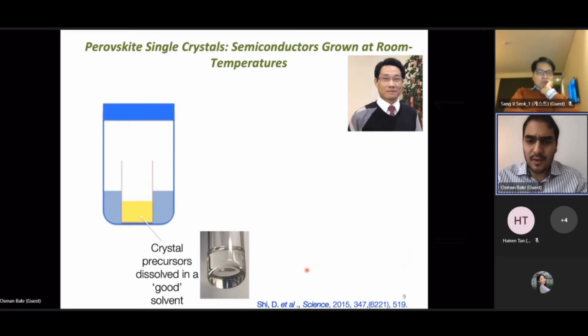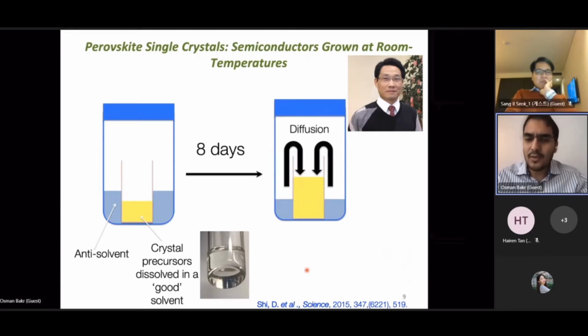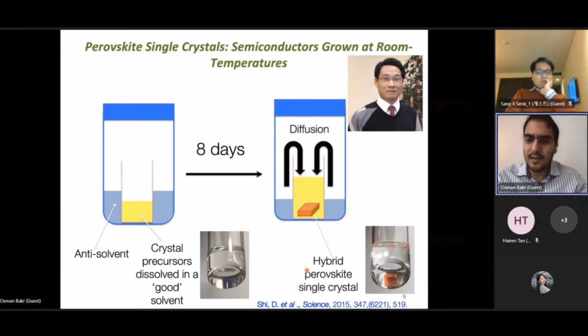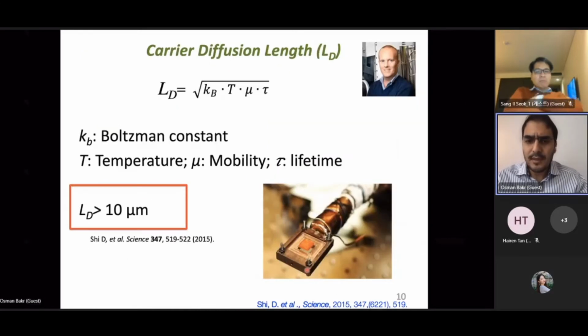We started crystallizing perovskites in a very simple way, and most people use these kind of crystallization methods in chemistry and biology, but actually no one applied it to perovskites at the time, or applied it to grow large perovskite crystals. And so we dissolved perovskite crystals in a good solvent and stored them in an anti-solvent, and over a matter of a few days to a week, we started getting the diffusion of the anti-solvent, and we started getting large crystals forming. And we wanted to look at the carrier diffusion, how far photoexcited carriers would travel, and we wanted to estimate that. So we could only do that at that time in an indirect way.